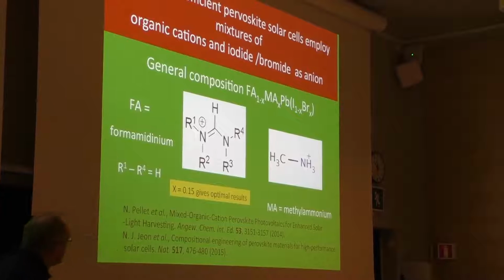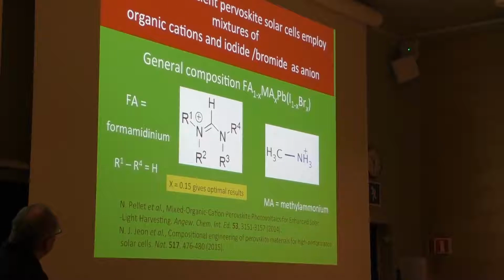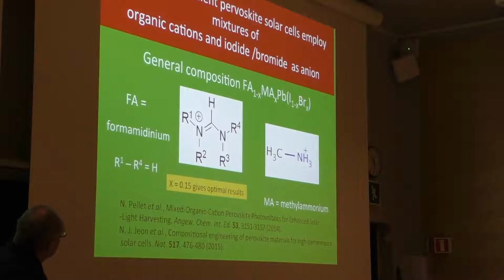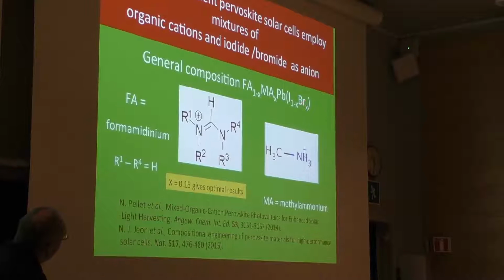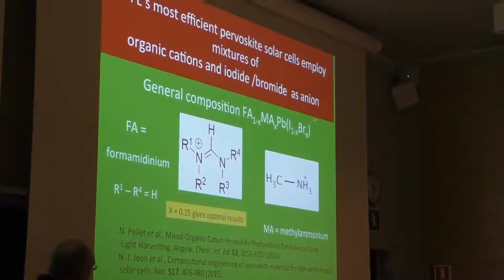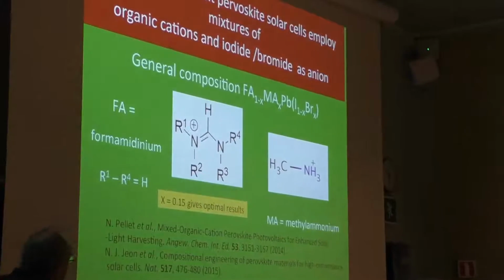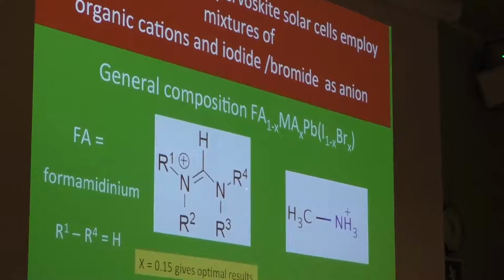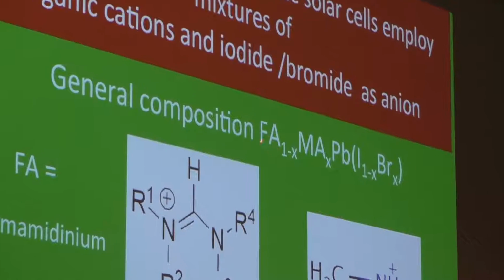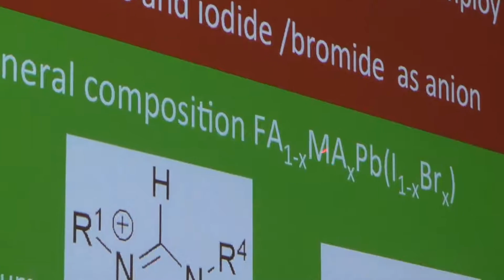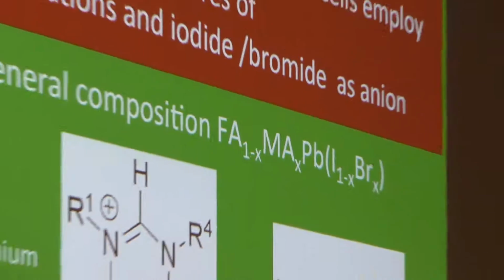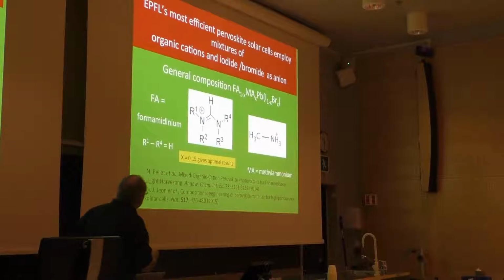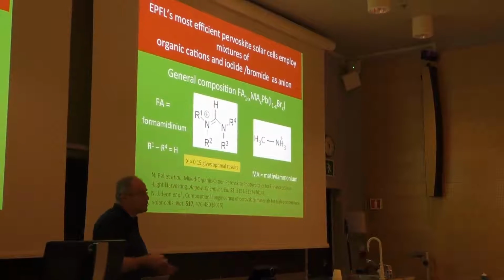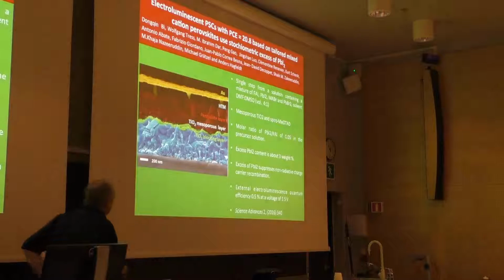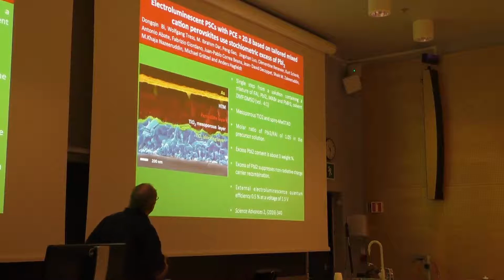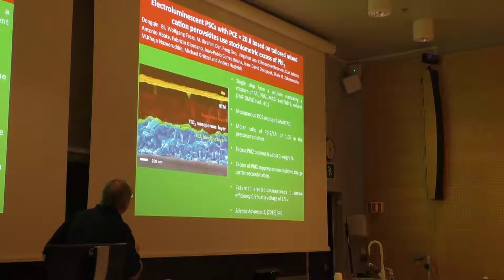Before I arrived at EPFL, they started to mix the perovskite. So here is 15% bromide, for example. It tunes the band gap a little bit to a larger band gap, but it also stabilizes the system. And you can also tune the different cations. So this is a mix of formamidinium and methylammonium. It also forms higher quality perovskite films, let's say. So this was the starting point to use a mixed system, and that we published early this year at about 21%.